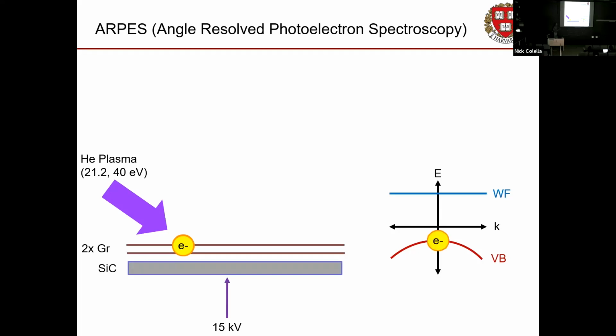And what happens? Well, okay. Same picture, electrons hanging out, and up it goes, right? And that's all good. But one thing's a little different. Since we're using monochromatic light now, if we had an electron that wasn't sitting, for those who know about band structure, right in the middle of our band structure, but had some momentum, somewhere on the dispersion curve, it's going to maintain that momentum and that energy difference when we do this, and it's going to end up going to a different spot in this diagram when we promote it up.